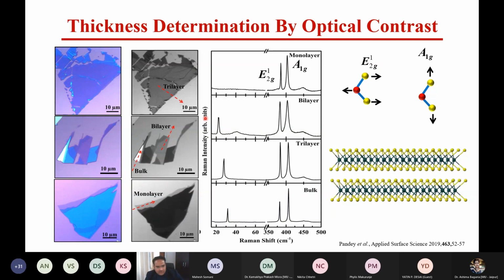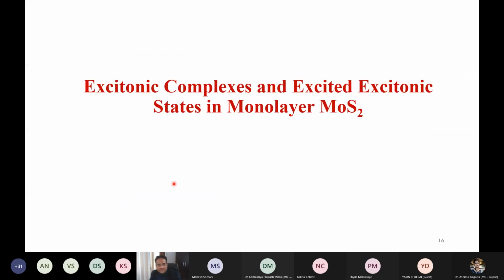So this is how you can identify, and you can see the contrast in the optical images here, and these are the processed images for the grayscale contrast, so that you should be able to find out what is the right thickness, okay. And this has been calibrated with the AFM for the thickness also, so it's a well-known technique right now. Anyway, so I'll go over the interesting aspect of these materials.